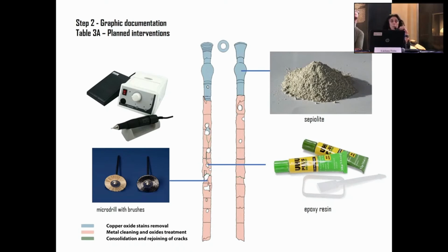And so a compress of sepiolite, of clay, on the organic parts can lead to absorption of the metal oxides, or even to lighten the stains, to eliminate the green stains on the surface. Then to reduce the oxidation. The oxidized parts are very dangerous because they continue working on the surface, leading to the complete loss of the metal.